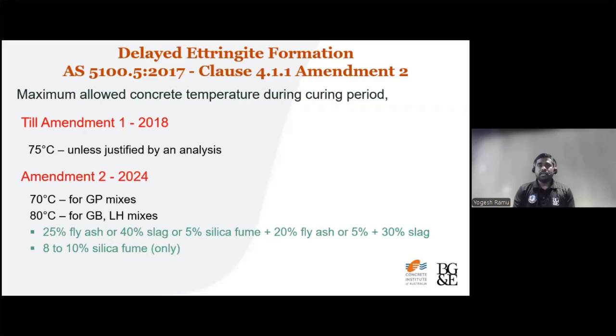Okay, so first, what are the changes made in 4.1.1 Amendment 2? Until 2018 Amendment 1, all the concrete mixes had to satisfy the 75 degrees Celsius maximum allowed curing temperature. Unfortunately, it wasn't differentiating between plain concrete mixes and concrete mixes with SCMs in them, although the performance is actually very different between an SCM mix and a GP mix in terms of strength development, heat of hydration and resistance to many durability issues.